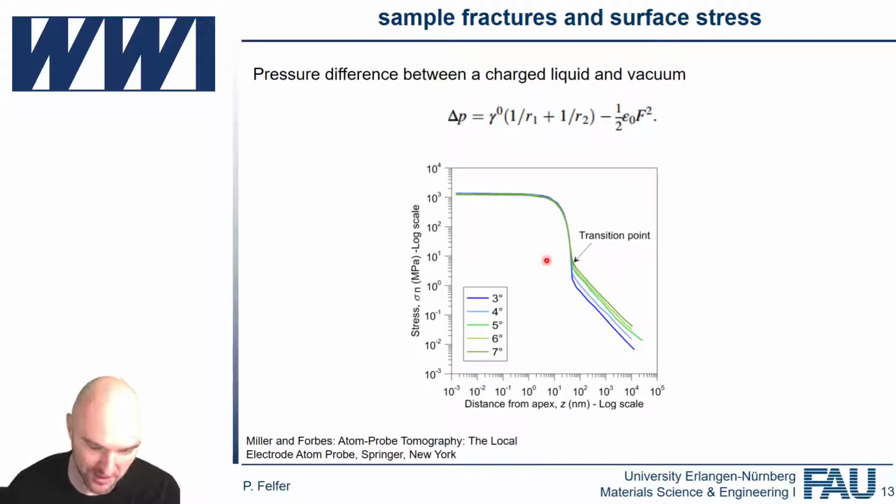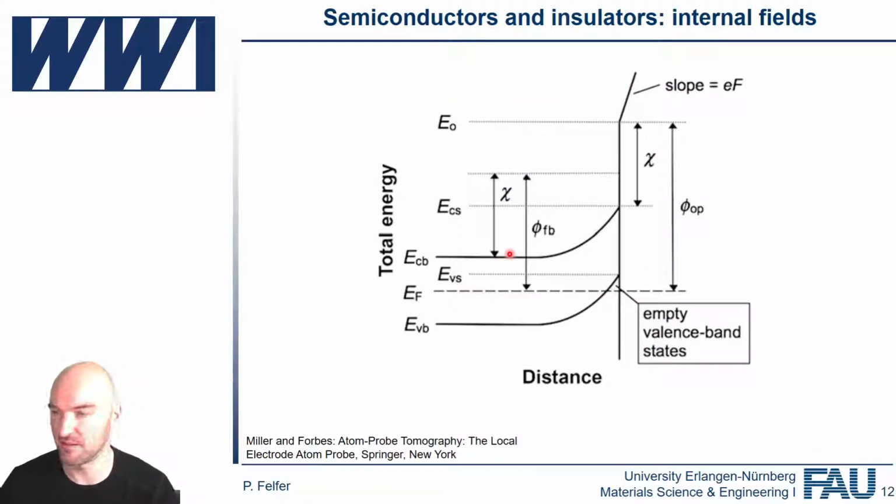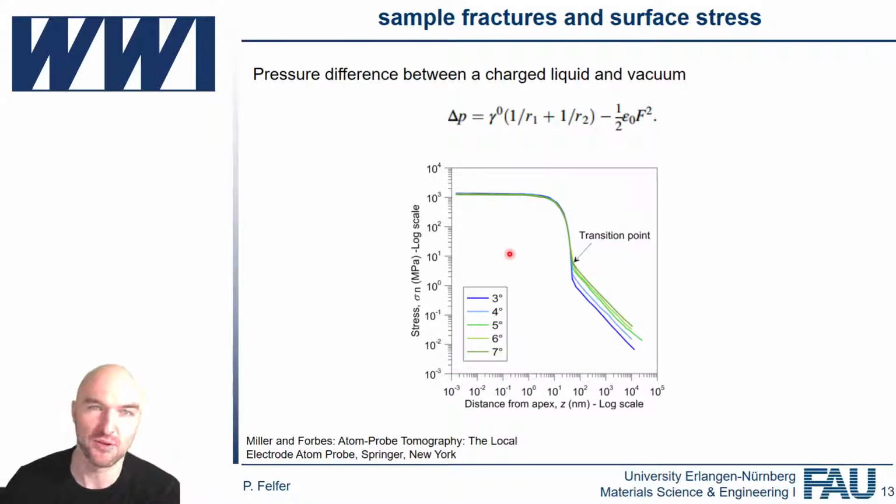But the field obviously exerts some force on the atoms. And the question for us is, does it make the atoms move inside? But it's also the question of, does it break our sample? There's a very nice derivation of that in the book from Miller and Forbes, where they show, as an approximation, the pressure difference between the inside and the outside of an electrically charged liquid. This is just an approximation for us. It is proportional to the field squared.